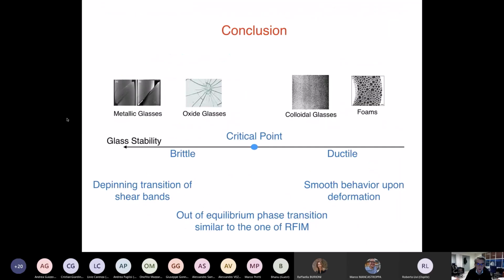So I will now conclude. What I wanted to tell you is that the way in which amorphous materials fail when they are deformed seems to be very different. Foams fail in a very smooth way. Colloids have an overshoot in the sigma versus gamma curve, and instead metallic glasses and oxide glasses fail very abruptly.